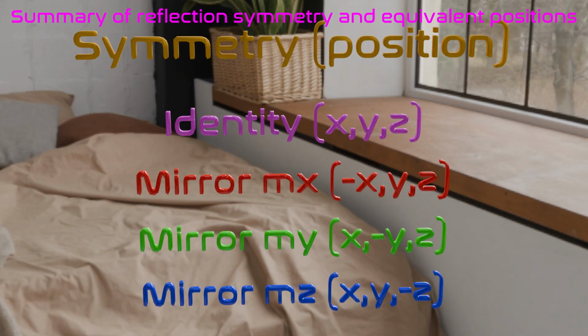Let's summarize what we've learned. Reflection symmetry gives us these equivalent positions. The identity operation keeps x, y, z unchanged. A mirror normal to x gives minus x, y, z. A mirror normal to y gives x, minus y, z. And a mirror normal to z gives x, y, minus z. These operations are the building blocks of crystal symmetry: simple, powerful, and everywhere in nature.